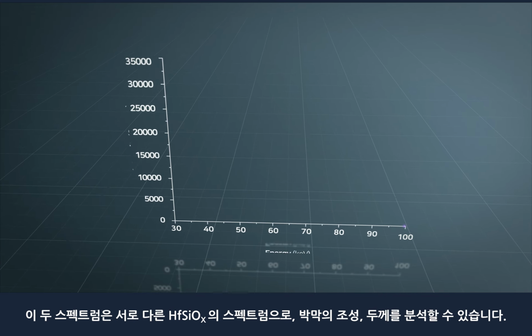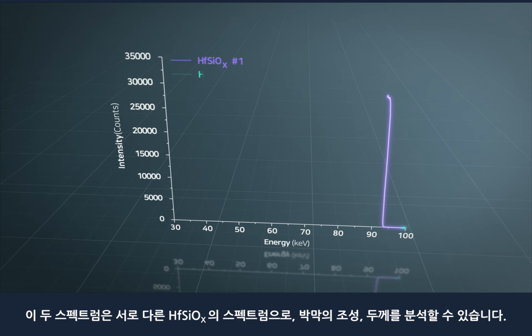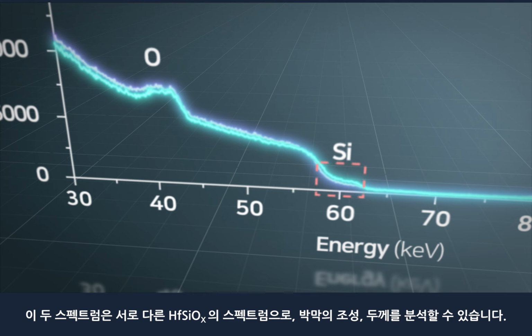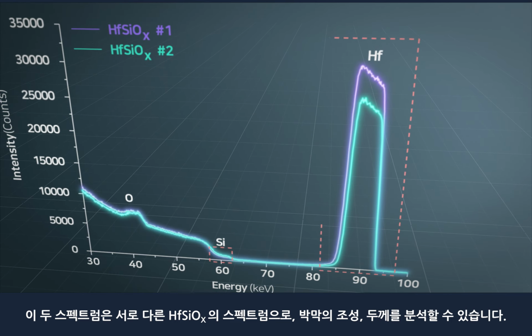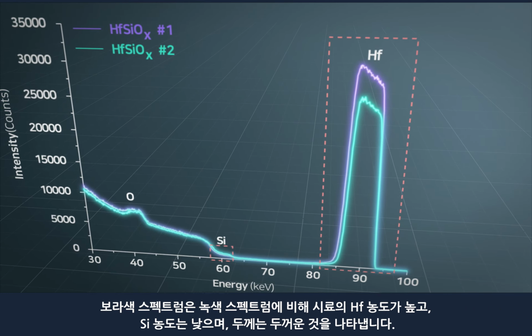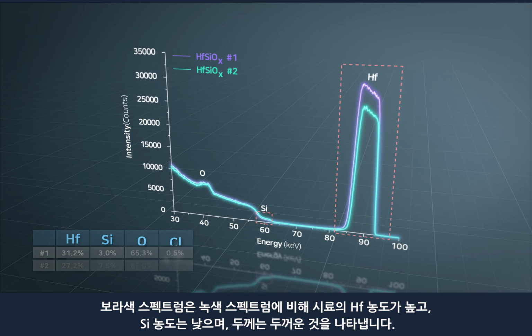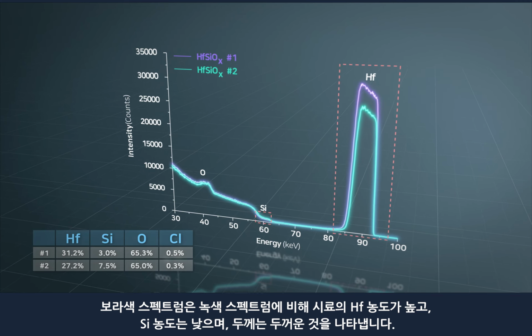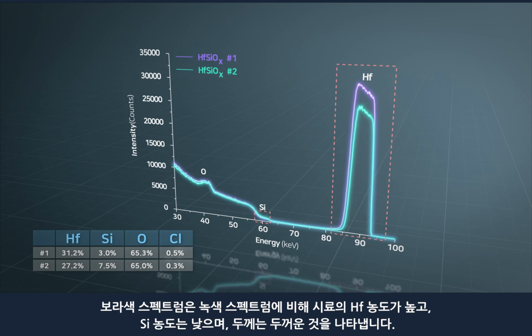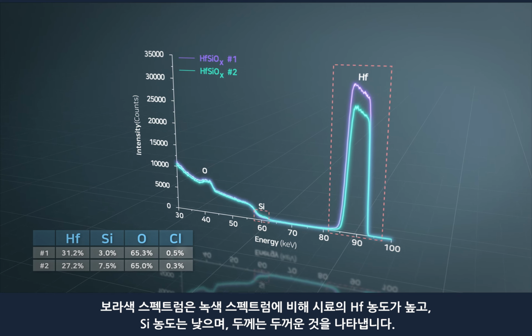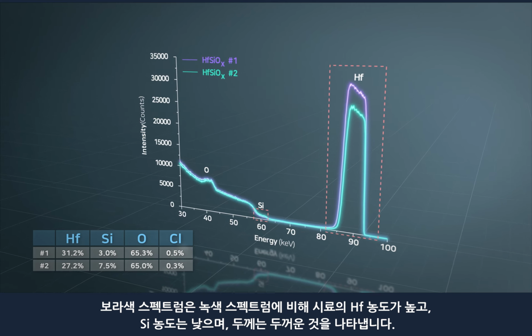This graph shows two different hafnium silicate spectra. The compositions and thicknesses of the thin films can be analyzed. As shown in the purple graph, the hafnium concentration is higher, silicon concentration is lower, and thin film is thicker in the purple graph than in the green graph.